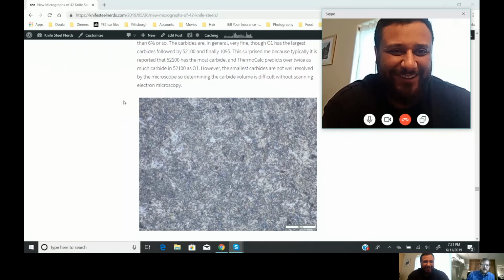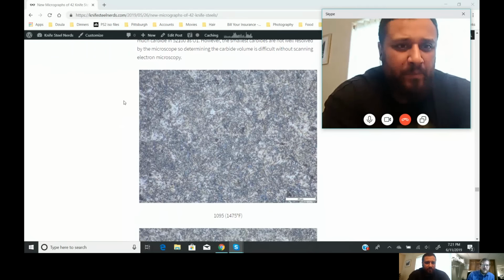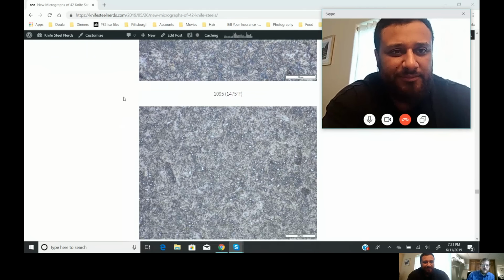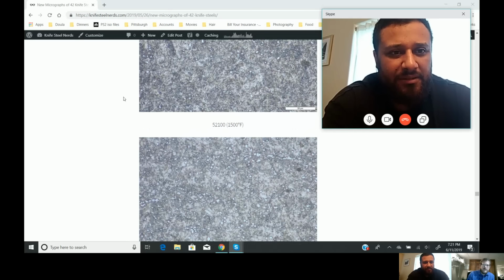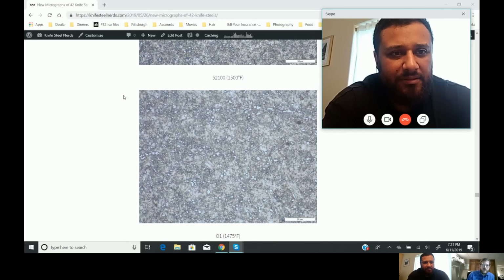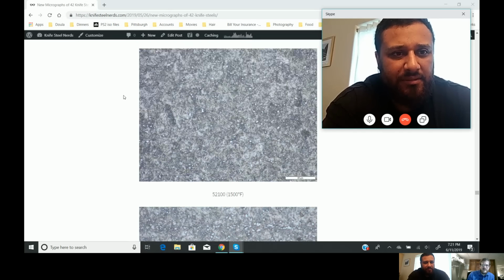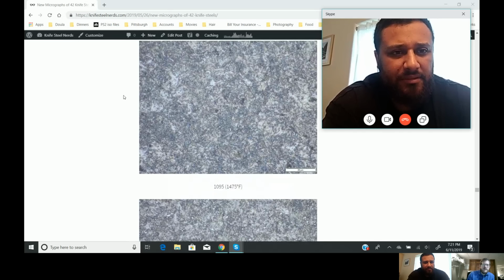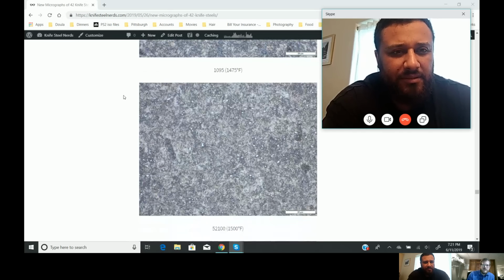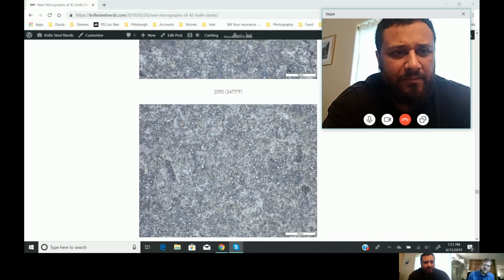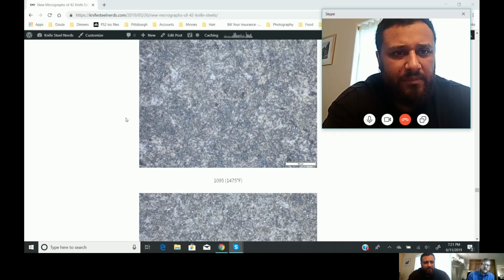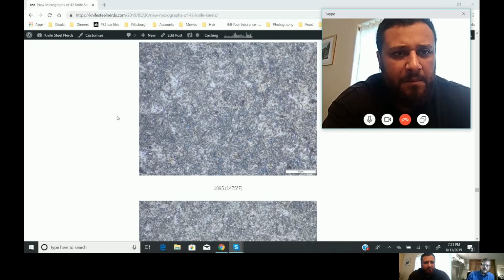Right on. Good stuff, man. Then we have the high carbon steels, 1095 and O1 and 52100. So O1 has larger carbides than either 52100 or 1095. One thing that surprised me was that in the 52100, the carbides are a little bigger than in the 1095. That surprised me because chromium is supposed to reduce the carbide size. So, interesting. Yeah, that was a surprise.